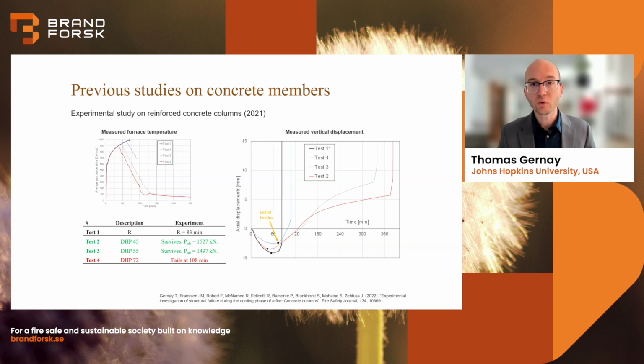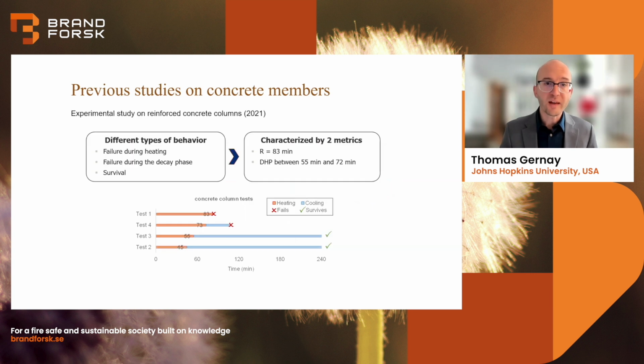That same column was able to survive the fires of 45 and 55 minutes. The columns were then loaded to evaluate their residual load-bearing capacity. And finally, in test 4, the column failed during the cooling phase when subjected to a heating phase of 72 minutes. You see the evolution of displacements as a function of time on the right. The blue curve is for this test 4, where you have the end of heating at 72 minutes, but the column eventually fails during the cooling phase. So for that column, the burnout resistance rating is between 55 minutes and 72 minutes. The column could survive the 55 minutes fire, but not the 72 minutes fire.